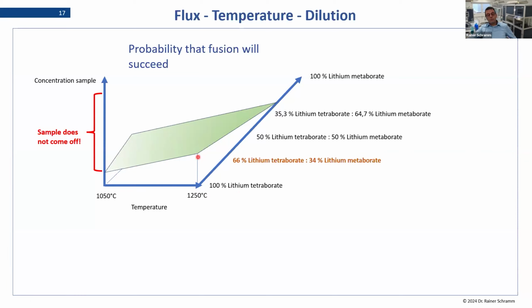And this means that while you change then to other fluxes which contain more metaborate, then it's reducing again, and then you have here a region where it's crystallizing. And I could say that this flux here, the 66 tetraborate and the 34 metaborate, this is a kind of universal flux because you see it's just in the middle. So it works more or less on all different kinds of parameters here. And you have a very stable phase. And this is why if you start with fusion recipes, you should always start from this flux. Then it's quite universal for what you want to set up.